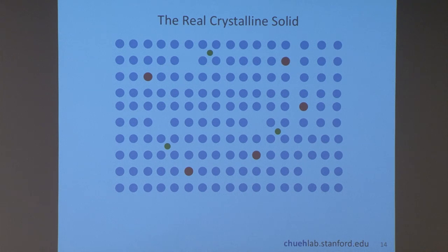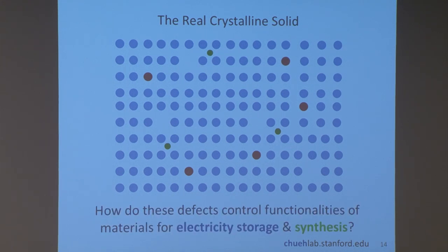And traditionally, when we look at these defects, we think, this is going to be problematic. In solar cells, the dangling bonds near these defects cause electronic states to localize. And this could become a problem for charge transport and recombination, lowering the performance of solar cells. But as I will show, these defects indeed actually control the functionality, in some cases in a positive manner, in materials for electricity storage in batteries, and also in chemical synthesis as well. So let me get started with the first one, in storage. What are the roles of defects, and how can we understand them and eventually make use of them?